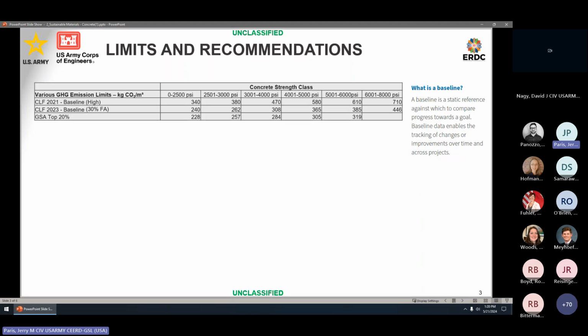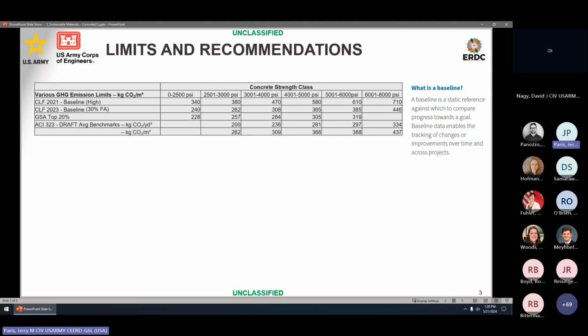If we look at the GSA values, there are different limits for the top 20 versus top 40 and top 80%. But what you'll notice is that the limitations to meet a top 20 for the GSA limits are actually even lower still. And then we get to the ACI 323 limits. These are draft benchmark values, and you'll notice that for each strength classification, they are considerably lower. And the main reason for that is ACI chose to do it in a different unit. So if you convert from their units of kilograms of CO2 per cubic yard of concrete into per cubic meter of concrete, these are the values that you get.